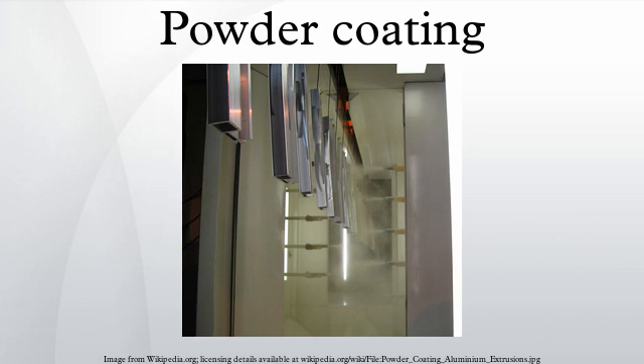Removing powder coating: methylene chloride and acetone are generally effective at removing powder coating, however most other organic solvents are completely ineffective. Most recently the suspected human carcinogen methylene chloride is being replaced by benzyl alcohol with great success. Powder coating can also be removed with abrasive blasting. 98% sulfuric acid commercial grade also removes powder coating film. Certain low-grade powder coats can be removed with steel wool, though this might be a more labor-intensive process than desired.